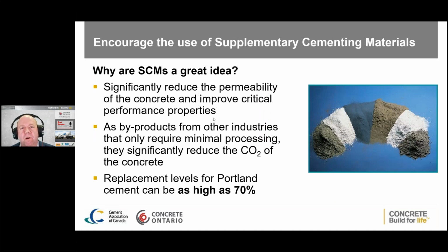Supplementary cementing materials, we talked about those before when I showed that table with various impacts broken out by materials. You saw the impact of using supplementary cementing materials. We've been promoting supplementary cementing materials for 50 years. They have a lot of positive impacts when it comes to reduced permeability, increased durability, increased compressive strength. There's a lot of other reasons why we want to use these materials, but they also have the added benefit of being a much lower intensity when it comes to carbon. So expanding their use really has a huge impact. And we're seeing, again, projects, mass concrete placements, for example, getting SCM replacement levels as high as 70% is not unheard of. So again, there's going to be more opportunities there.